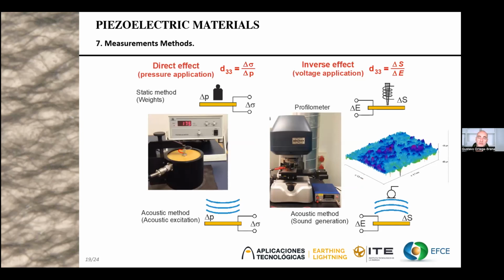Okay, the piezoelectric coefficient can be measured in two ways, by quasi-static and dynamic measurement. This is because the response of piezoelectric material changes with frequency. Each of the two methods can be done by direct effect, by applying a force, or inverse effect, by applying an electric field. As for the direct effect, commercial devices can be found in the figure on the left, where the sample is pressed at constant velocity and the charge is measured directly on the display. This device works at low frequency.